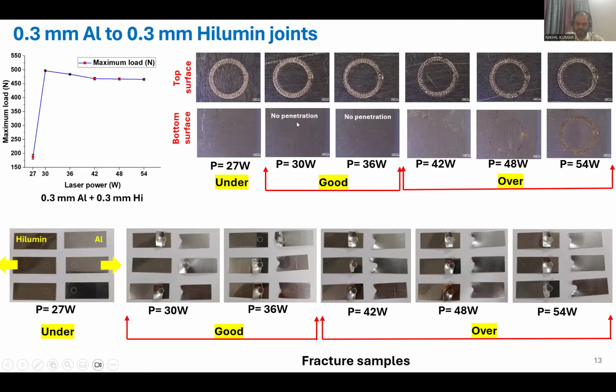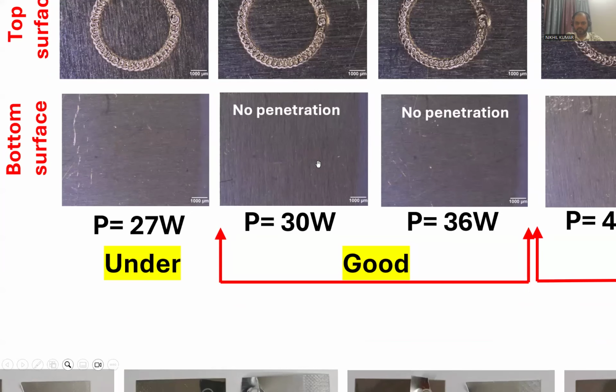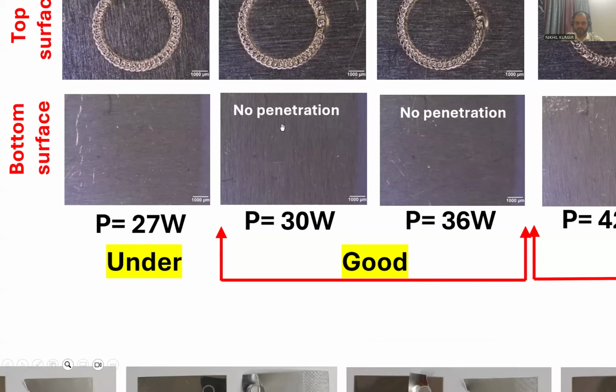The next one is the 30-watt power. Here you are getting very good strength, equivalent to 500 Newton. Here the top sheet is failing. It's broken, and there is no interfacial failure. So you can consider this a good weld. Why is this considered a good weld? Because it fulfills the welding definition, and there is no bottom sheet penetration on this particular parameter.